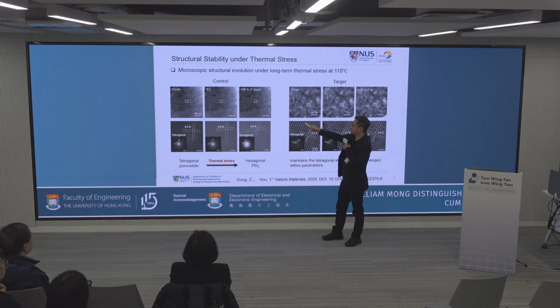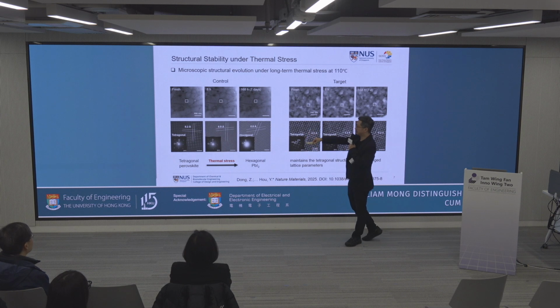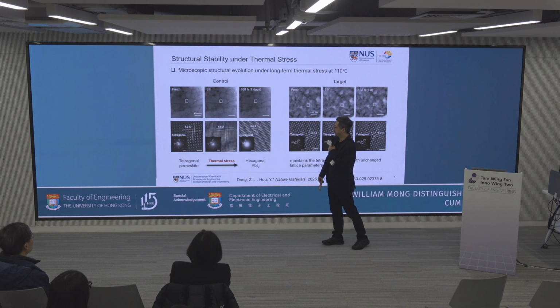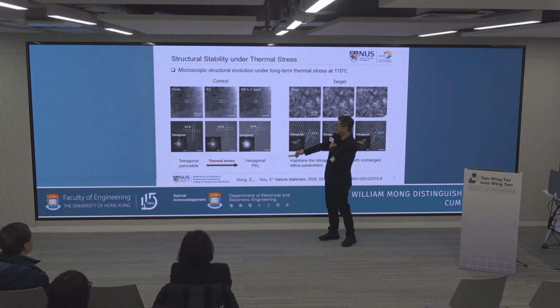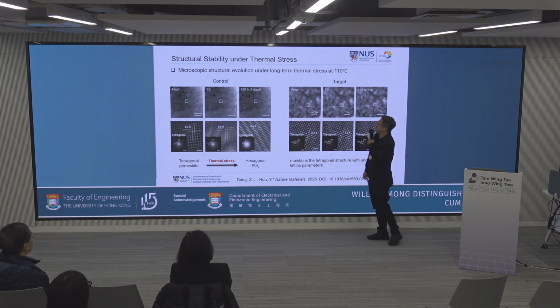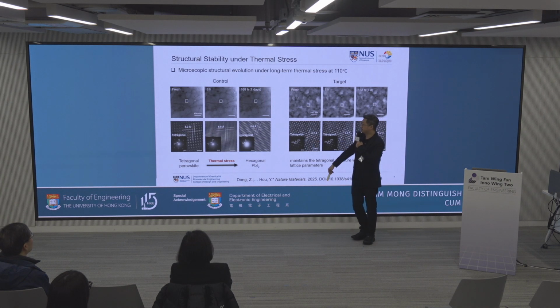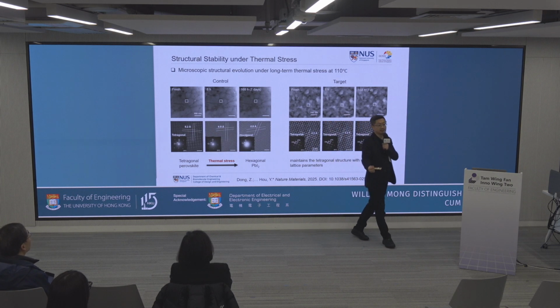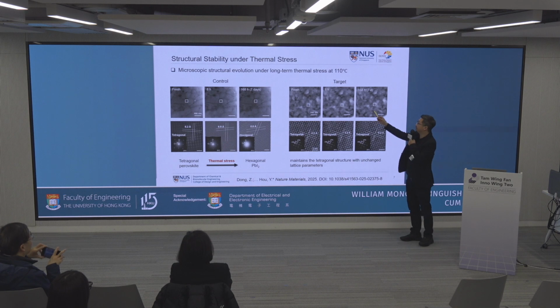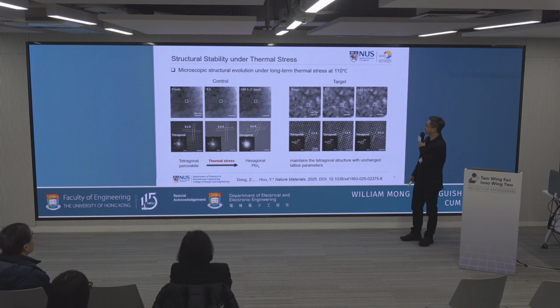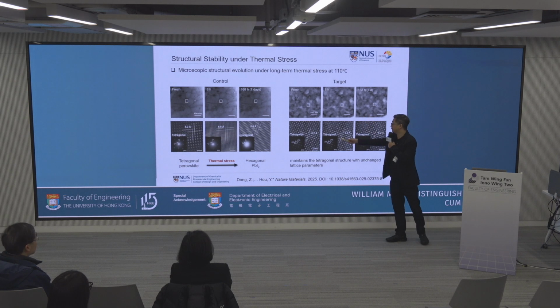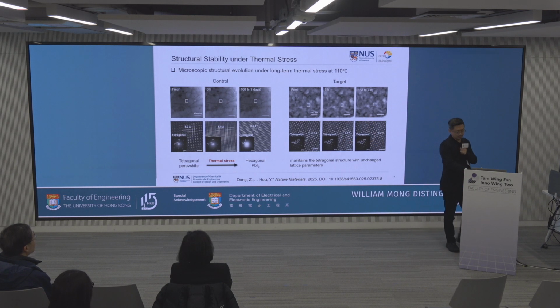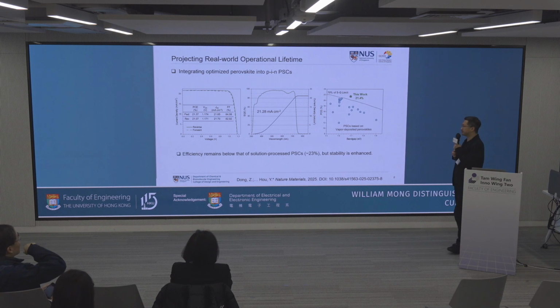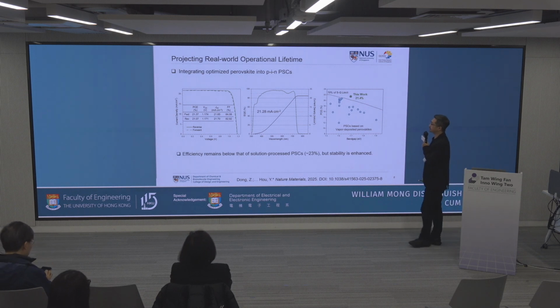And so if you look at the stability and the halide and the TEM measurement, then we can check the perovskite, the control device. And if you look at this, it's a tetragonal phase. But if aged for a very long time at 110 degrees C, you can see after quite a long time, it becomes a hexagonal phase, which is lead iodide. It indicates the perovskite is degraded. But with our fully evaporated film, you can see after this long aging, the perovskite can still maintain this tetragonal phase.